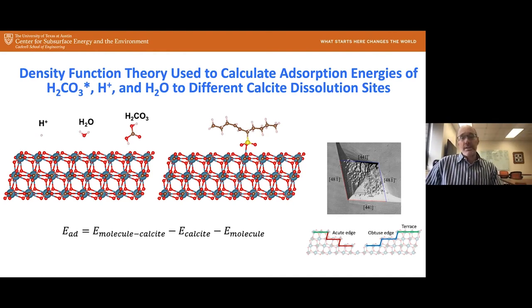The other approach we use, and this was in collaboration with Graham Henkelman and his student Yagana that I mentioned at the beginning, is using density functional theory. And so here what we wanted to do is calculate the adsorption energy of these different molecules on the surface of a calcite. And we wanted to do that at different calcite sites, which would include the acute edges, obtuse edges, terraces, and then the kinks. And so first we calculate just the energy of a single molecule, i.e., carbonic acid, water, and proton. Then we calculate the energy of the calcite. Then we calculate the energy of the molecule bound to the calcite at the most favorable location or configuration. And from that, we calculate the adsorption energy.